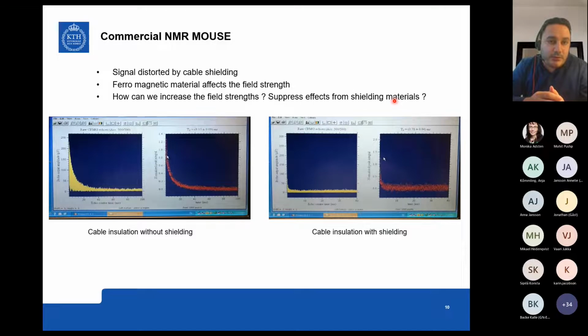So what we did was that we quickly tested it on the NMR mouse to try to see does it work. So the image to the left is essentially a cable insulation where we simply took out every form of steel component from it and just kept the polymers and primarily the cable insulation, which was of interest. So we saw that, okay, fine, we can get a signal from the polymer without any form of interference from any steel. The image to the right is when you don't do anything at all with the cable.